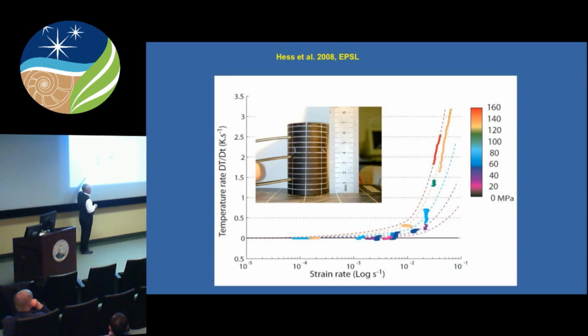We always try to keep the samples 10 times larger than the largest inclusion. And there you see, and it may sound like a trivial result, it's one that you in principle can predict in theory, but measuring it is a little more difficult at 600 or 700 or 800 degrees Celsius under a deforming system where there's an active temperature control calibrating for any temperature changes in your system, which is the way all of our high temperature controllers work. But you can see that there's a rise in temperature which takes off, but we can measure it already beginning at 0.5 or 1 degree Celsius at 600 to 800 degrees Celsius.